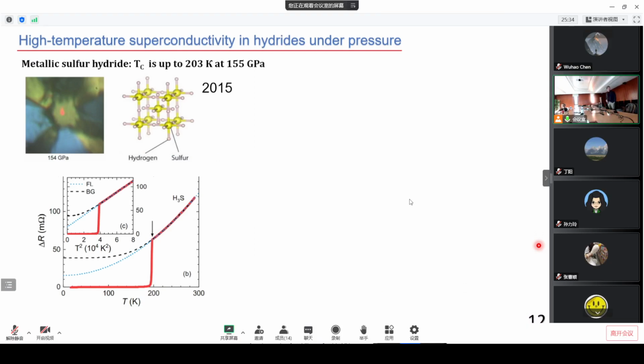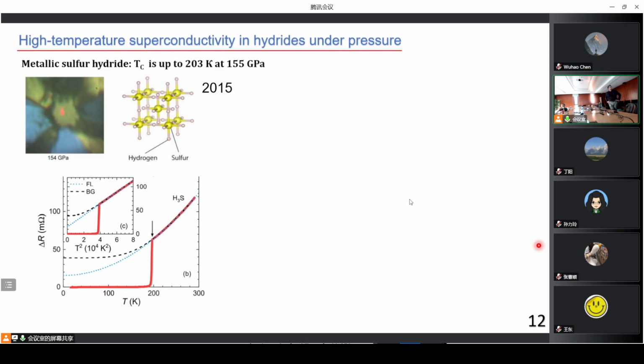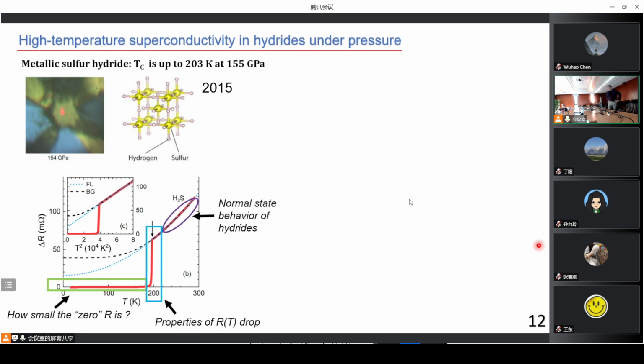As we all know, the story of superhydrides began in 2015 when the group of Mikhail Eremets and Alexander Drozdov discovered remarkable superconductivity in metallic superhydrides at a pressure of about 155 GPa. The TC may reach 200 kelvins. In the subsequent years, between 2015 and 2022, people studied several questions, like how small the resistance is in the superconducting states of polyhydrides. They also studied the properties of the sudden resistance drop, and how it behaves in magnetic field with different frequencies and with different currents. But they mostly didn't pay attention to the normal state behavior of hydrides, and now I will show something interesting in this field.